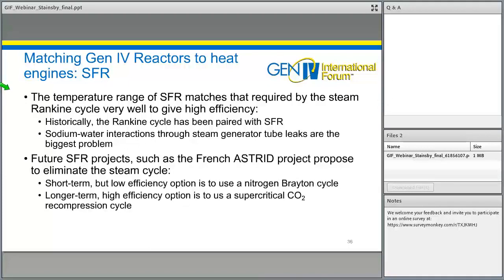So if we look at them in turn, for SFR, all the sodium-cooled fast reactors in the world so far have actually been paired with Rankine cycles, and they've worked with reasonably good efficiency. Certainly the PFR plant in the UK was delivering around 40-41% thermal efficiency using quite a highly optimized steam plant, but it's a steam plant nonetheless. The biggest problem with sodium-cooled fast reactors to date has been steam generator tube leaks.